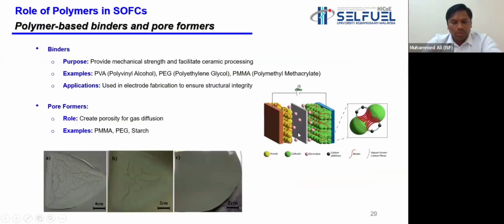And then I talked about fabrication of these fuel cells. I said it's quite complex when we are fabricating bigger size fuel cells. So we go for advanced fabrication techniques, mainly solution-based techniques, where we need to produce inks. When we are formulating an ink, the solid content of that ink will be like 60%, 65, or 70%. The remaining 30% is polymeric material. We use binders, surfactants, plasticizers. What these binders do is improve the mechanical strength, and also facilitate the ceramic process.